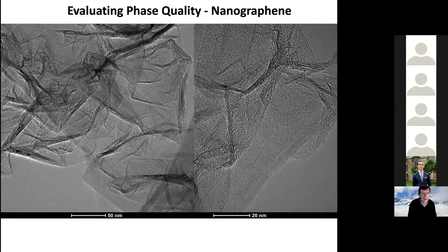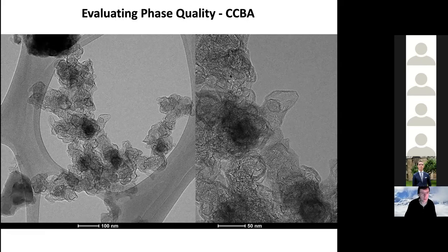those particles. Just to give a little bit better resolution, higher contrast for the 2 products of interest, again, the nanographene, you can see multiple sheets, crumpled, folded. Much of this is probably due to our processing for the deposition on the grid itself, so this is not necessarily inherent to the process. But what is inherent is that it is few-layer graphene. You can see on the right-hand image the number of steps, number of layers offset from one another. And so these are very highly crystalline materials by selected area electron diffraction, which I'll come to in a few minutes.